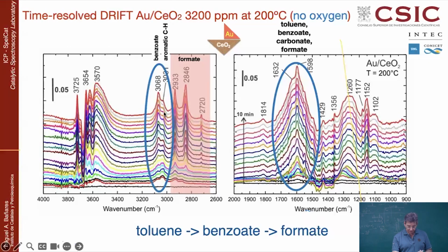band of aromatic CH, which is the toluene, but very quickly, in a few minutes, you start to see the development of benzoate, which is already a more oxidized molecule that derives from the oxidation of toluene. And the interesting thing is that you are adsorbing toluene at the surface of gold at 200 degrees C without oxygen. So this is already because of the lattice reactivity, it is already converting the toluene into benzoate.